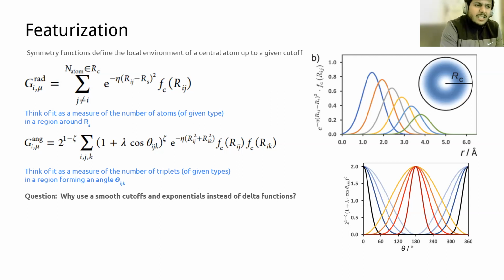And third is more of a convenience aspect, and the fact that we will have to run molecular dynamics or geometry optimizations or compute phonons. So these representations better be smoothly varying. You don't want them to change abruptly. So that's why generally you have these cutoffs or functions which basically go to zero beyond a certain distance. For example, you can see that everything beyond 6 angstrom is definitely zero. In this case, unsurprisingly, that was our cutoff that we chose, right?